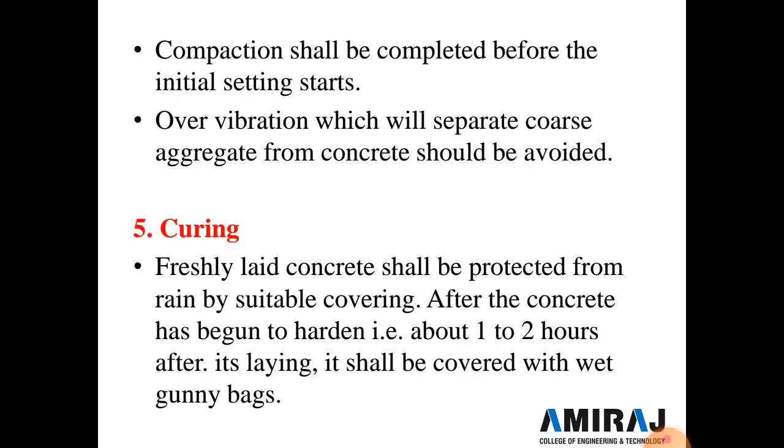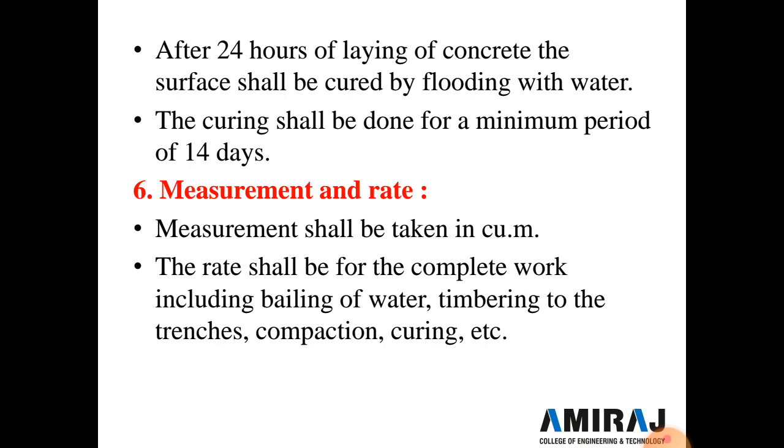After 24 hours of laying of the concrete, the surface shall be cured by flooding with water, or by sprinkling of water, or covering with wet absorbent materials, and the curing shall be done for at least 14 days. So a minimum 14 days curing period is compulsory for RCC work or concrete work.